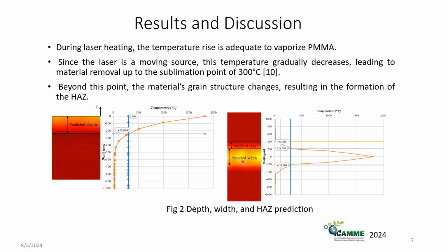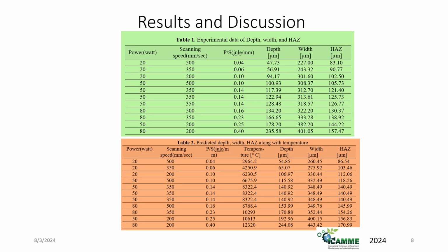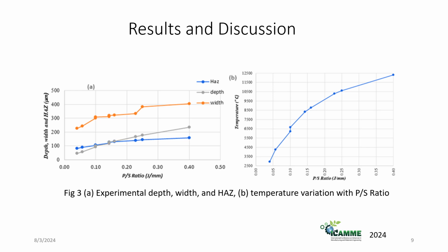Similarly, in the middle of the channel width, temperature was highest and it gradually decreases towards the wall. Until 300 degrees Celsius, we get the channel width, and beyond this, until 110 degrees Celsius, we get the heat affected zone. This table shows the experimental data of depth, width, and heat affected zone, and also the predicted depth, width, and heat affected zone, along with the temperature. All the response parameters, depth, width, and heat affected zone, increase with the increase of P by S ratio, because as the P by S ratio increases, temperature increases, shown in figure 3b.